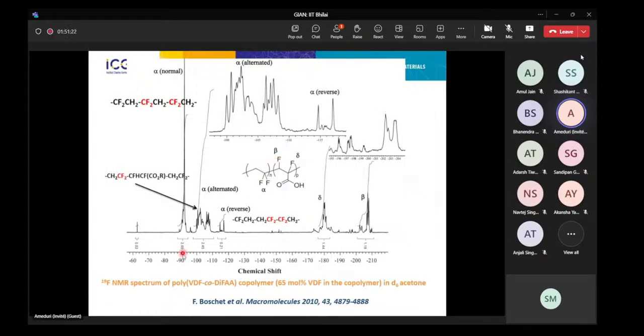And indeed, when we see this nice signal at -92, this is assigned to VDF units in a row, which is called the head to tail, while in the case of what is called the dyad, VDF adjacent to our alpha-beta compound, we have a shift on the signal. The CF here, the beta and delta are linked to the two fluorine of the system. And so from the integral of the characteristic signals, it was possible to calculate the content of VDF. So in this case, we have 65% VDF, sorry, in the copolymer. So this was very interesting.